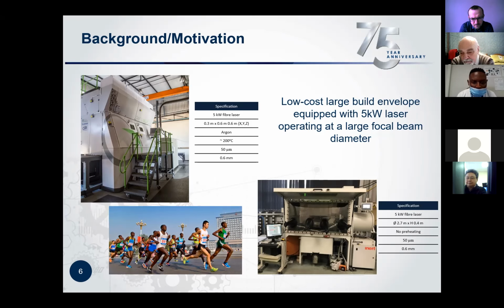The professor also mentioned that we have a smaller version. We call it the Hummingbird, which is exactly the same as the AeroSwift in terms of the parameters. It's also equipped with a 5 kilowatt laser. We designed this system so that we can do all our process development there. We can do a variety of materials. Obviously, with the bigger system, we cannot be playing around with different materials. There's a high risk of contamination, but with the smaller system, it's easy to manage. We can easily switch between different materials from titanium to aluminum and stainless steel. So yeah, SLM Solutions is already ahead, but we are still in the race, and we hope that one day we will be able to achieve the goals that we initially set for ourselves.